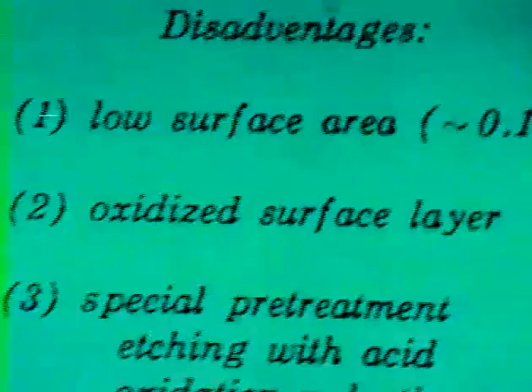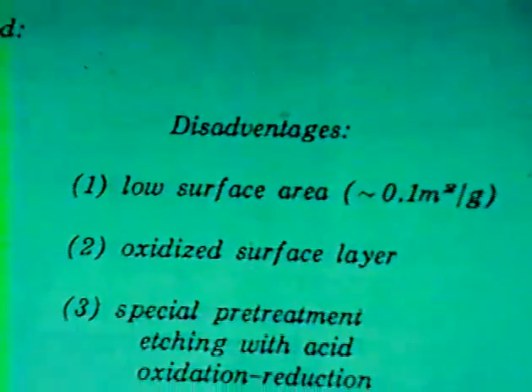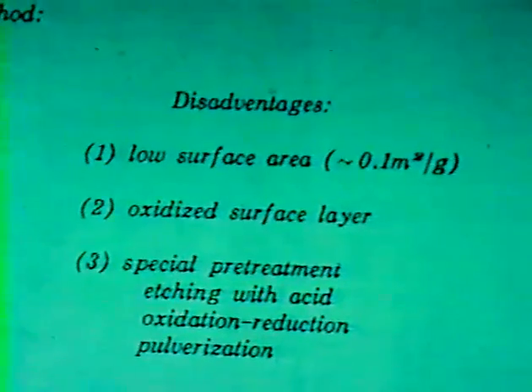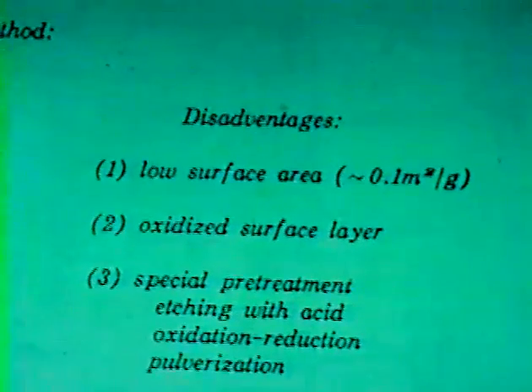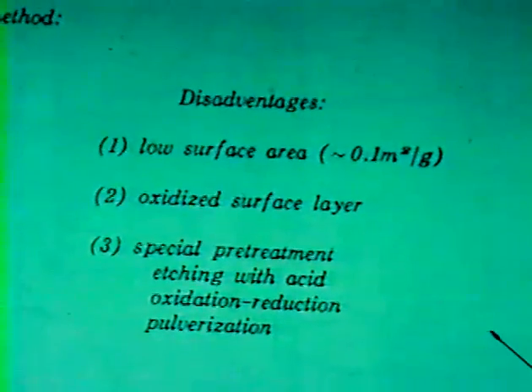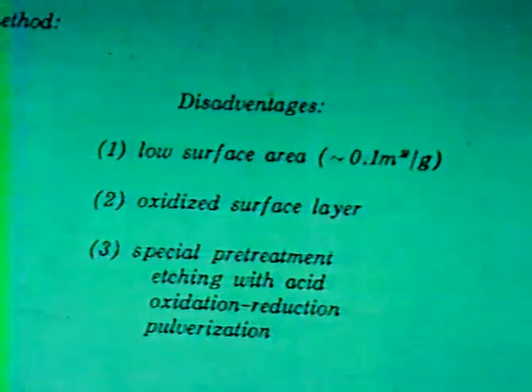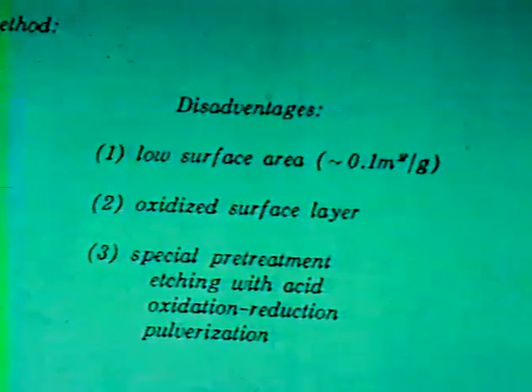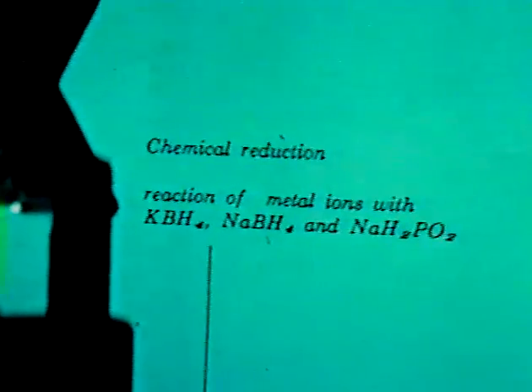Most of the amorphous alloys used in previous studies were prepared by the quenching method. The amorphous alloys prepared by this method are in the form of ribbons or films. These ribbon alloys and films have some disadvantages when used as catalysts. The first is the low surface area, and the second is the oxidized surface layer. So special pretreatments are necessary to activate the catalyst. The pretreatments include etching with acid, oxidation-reduction, and pulverization.